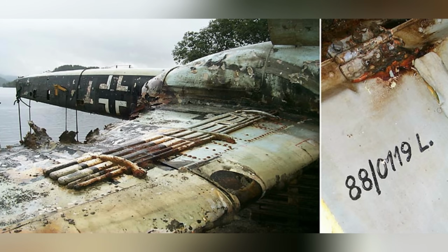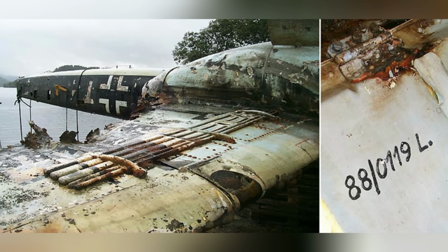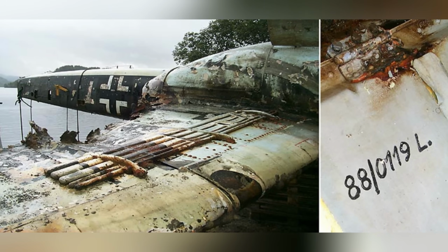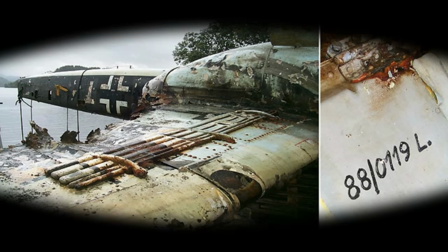The aircraft was not covered in rust or marine growth. It was coated in a fine layer of gray silt. Underneath this sediment, the paint was preserved to a degree that is rarely seen in aviation archaeology. However, the exposure to the air immediately activated the corrosion clock. While the aluminum was stable, the steel fittings, control cables, and remaining iron components were now vulnerable to flash corrosion.